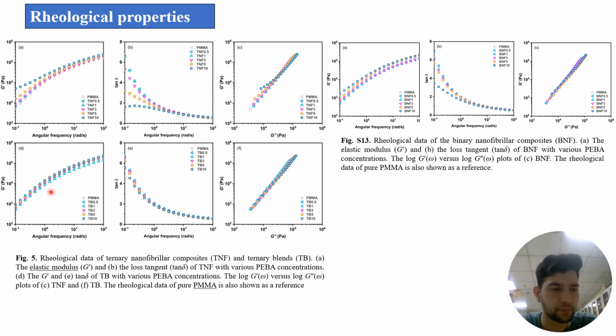While figure 5D and figure 5E show elastic modulus and loss tangent for the ternary blend. When PEBA is dispersed in a spherical shape, spheroids, in the ternary blend, we can see there is no significant variation. There is no significant change observed in the elastic modulus and the loss tangent. And figure 5C and 5F are log G prime and log G double prime.